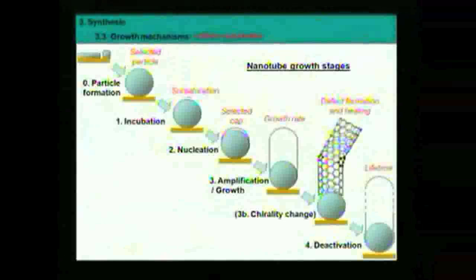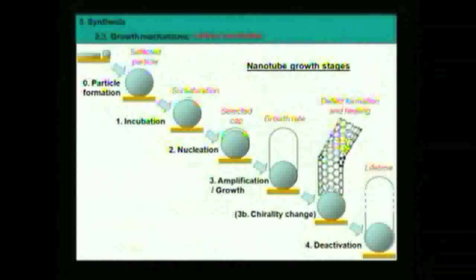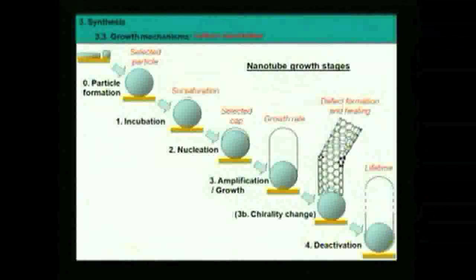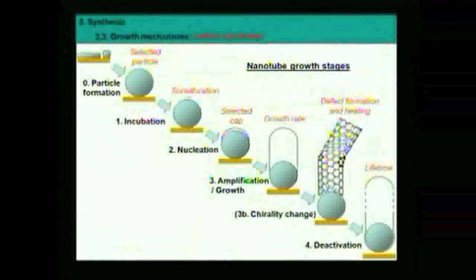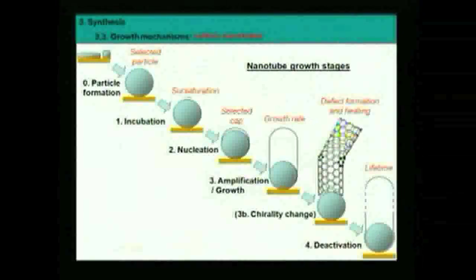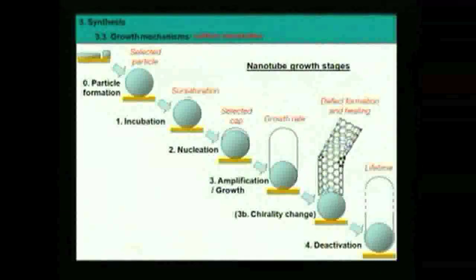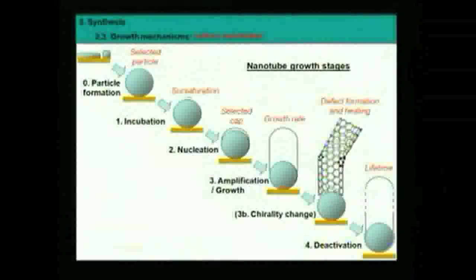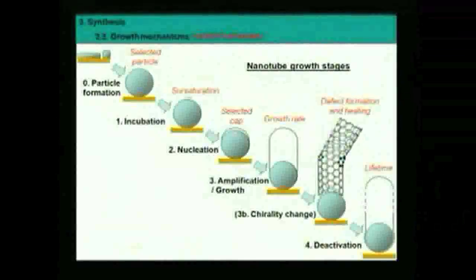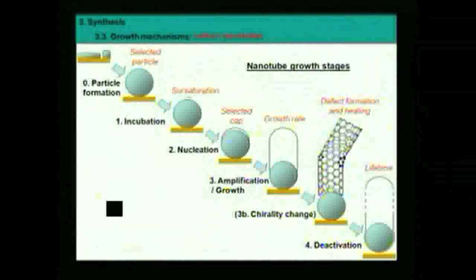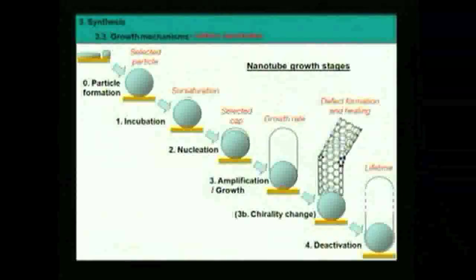And in this mechanism, we have first the formation of the particle, something we haven't seen in the movie, but that has to be done. We've got the particle on the substrate. We put some acetylene at the surface. It is dissociated. We got carbon atoms at the surface. And at some point, there are enough carbon atoms to make a first stable nucleus. And this is really an analogy to crystal growth. You know that in crystal growth, you need a critical size. There is a critical size of nucleus. Below this size, this nucleus, the seed, is not stable. You need to reach this critical size to start growing a larger crystal. So you need to reach the saturation of your solution, for instance.